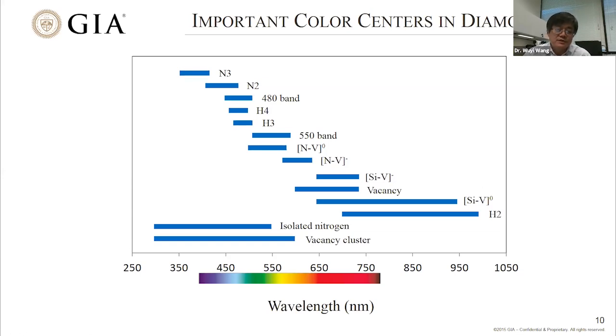Here, what I try to show first is the human eyes can see the range from about 400 nanometers to about 700 nanometers. That's what we see as visible light. And what I show here are the major defects that selectively absorb a range of visible light. For example, if I use this NV neutral and NV negative defect here, they absorb basically everything from green, yellow, orange. They absorb this whole range, and then the diamond will have a red area that's transparent. Basically, red light would be able to go through the diamond. That's why we see a diamond could show red color, or if the concentration is low, that could be a pink color. That's how it works to create a color in a diamond.